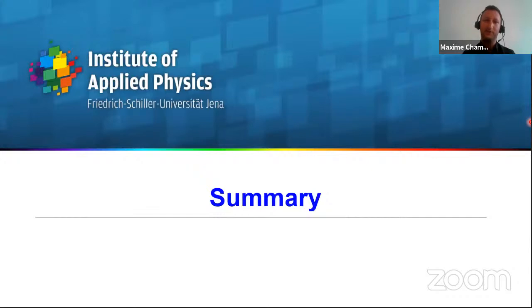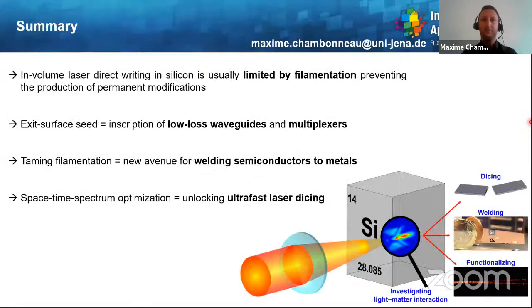So, to summarize, as we have seen, in-volume laser direct writing inside silicon is usually limited by filamentation, which prevents the production of permanent modifications inside the material. However, if one uses exit surface seeds, like crater production at the exit surface of the sample, it is possible to perform laser inscription of low loss waveguides and multiplexers inside the material.